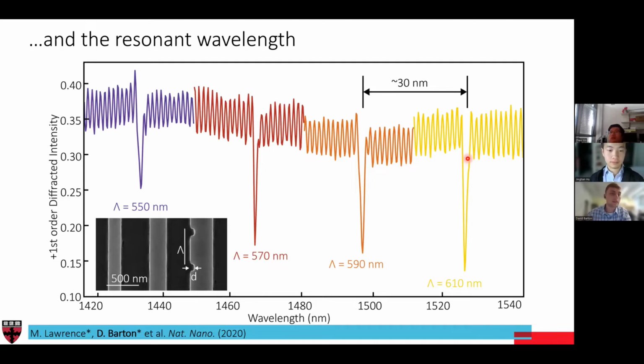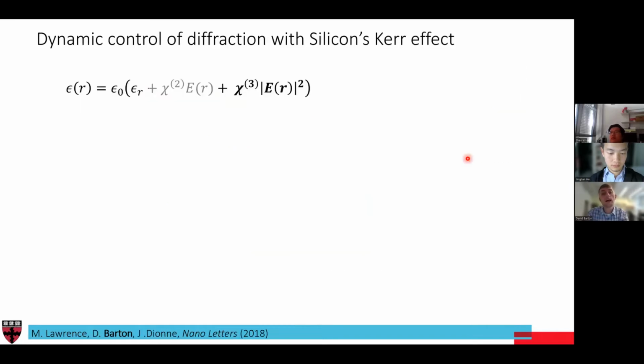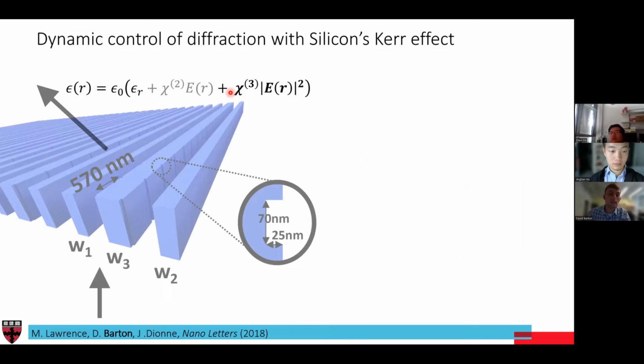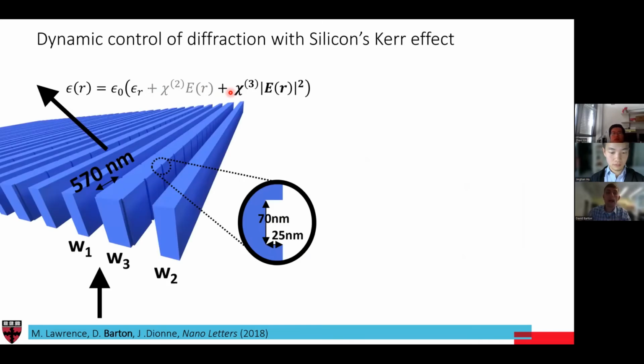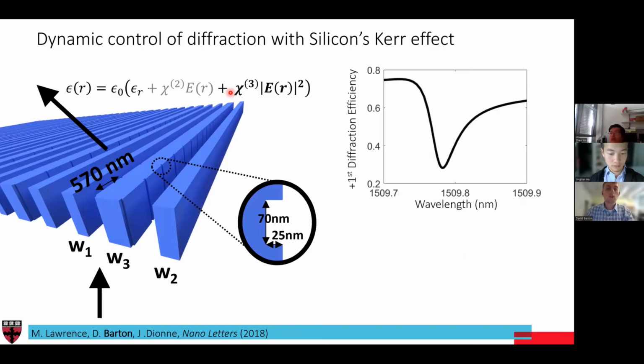And this is built in silicon, which, as I mentioned, is centrosymmetric. So it does not have that chi2 parameter, but it does have this chi3. And so we played a couple of games with how we might be able to do interesting things with this. So the first thing that we did with this structure is to say, well, what happens if we crank up the power? So in this structure, we were able to design nanostructures where we have a reasonably high quality factor, again, in this sort of beam steering response.